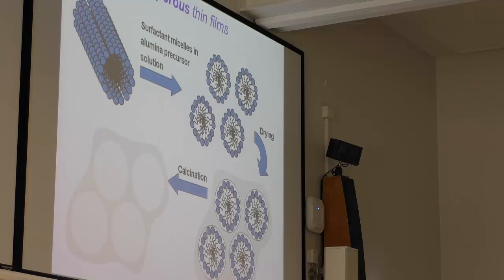So as you probably know better than I do, the way to do this kind of stuff is that one puts surfactant micelles in, for example, alumina or silica precursor solutions. This is the sort of Sol-Gel technique. One can have micelles forming, and when this solution dries up, one can make them spontaneously self-organize into various crystal structures, and then in subsequent calcination steps, one can make the precursor solidify, if you like, and at the same time burn away the organic materials.